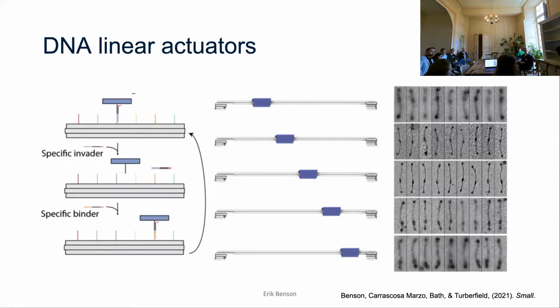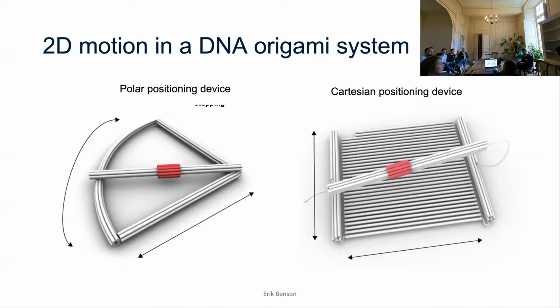How we started was with the simplest type of DNA motor you could build, which is a linear actuator. We had something that looks like a rotaxane, in molecular machines chemistry, but bigger. It's around 200 nanometers long, and it's composed of 2 DNA origami components. This ring, in blue, is linked along a beam, a rotaxane along a beam, where it's topologically locked. It's free to diffuse along the beam. But if we add specific address strands, we can drive it into one position in 1 dimension.